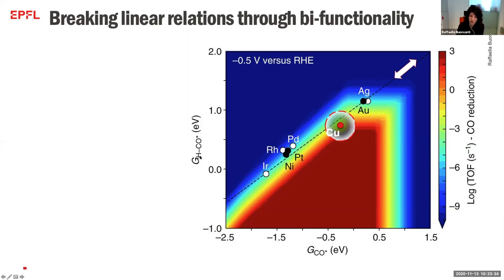However, if we want to stabilize further this intermediate and so promote further the electrochemical CO2 reduction, we find problems, because if we move towards catalysts which bind this intermediate stronger, as I mentioned before, we also poison these catalysts because they will bind strongly also the CO. And this is because all the CO2 reduction intermediates bind to a carbon atom.